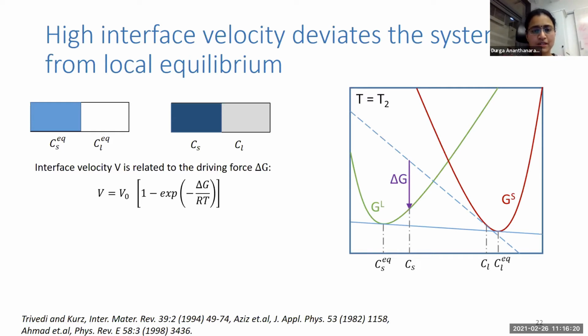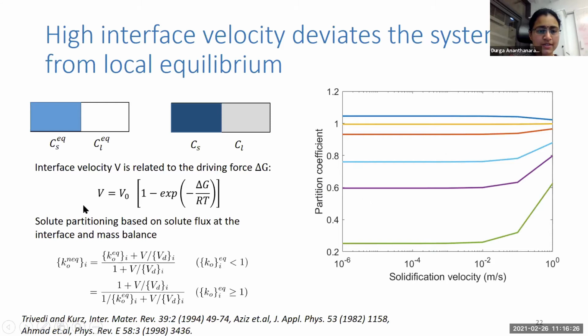From this, we can get the composition of solid and liquid. One more relation that's required to determine this completely is the partitioning of the solute itself. Based on the solute influx at the interface and mass balance, and with a lot of simplifications, we have this Aziz model, which is also commonly used nowadays to represent this non-equilibrium effect.